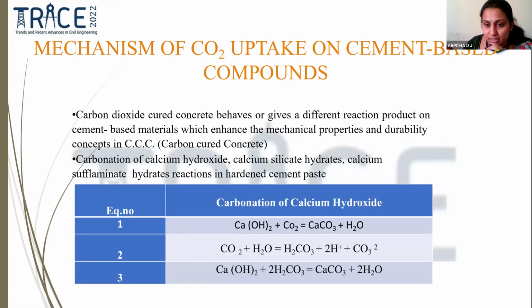This is a very important step, from the reference of 10 to 12 papers. We will see the mechanism of how exactly carbon dioxide uptake occurs in carbon cured concrete. When we are curing the concrete, carbon dioxide gives a different reaction that makes the carbon cured concrete mechanically and durably, thermodynamically strong. That means calcium hydroxide, calcium silicate hydrates, and calcium sulfoaluminate reactions make our concrete harden and become more dense than normal conventional concrete. These are the carbonation equations for the calcium hydroxide liberation and leaching in the concrete, as derived from different papers. These equations show how the mechanism is involved in carbon dioxide curing, in concrete cured by carbon dioxide, and also with the usage of recycled aggregate inside the concrete. Next, ma'am.